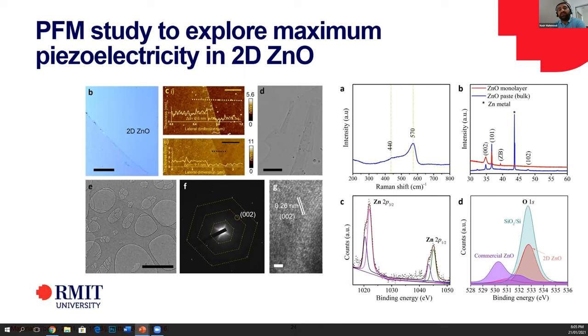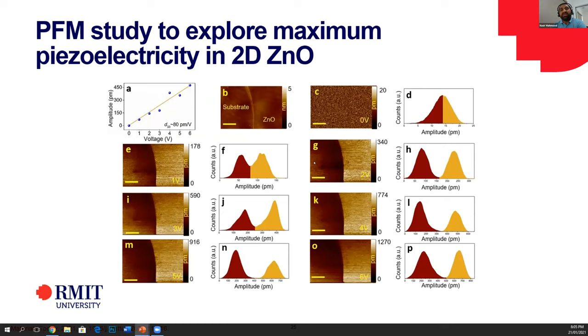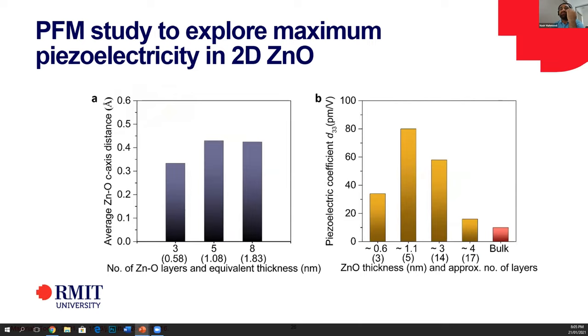Here you can see some of the PFM characterizations, which show the phase changes when we apply different potentials. When we plot that, it gives a value of 80 picometer per volt displacement, showing a higher coefficient. We further studied whether reducing thickness is important, and reduced the thickness up to half a nanometer. We found that when we move from one to a half nanometer, the response is reduced again. So thickness creates more and more displacement, but there is also some strain and the metallic nature of the zinc oxide contributing. The best thickness where we balance all these factors is 1.1 nanometer.